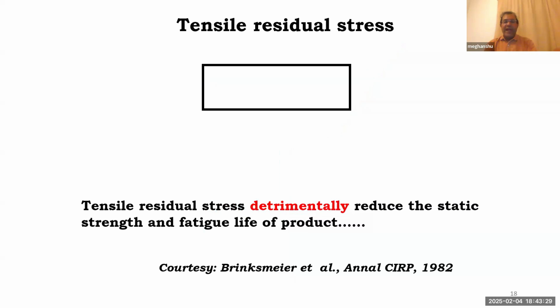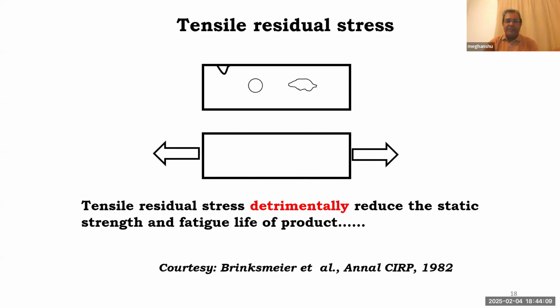So, if we consider this block as a component and this component is having cracks at surface level, the component is also having void or free space. It is also having some porosity. So we know all manufactured components or any produced product is not 100% accurate because it is having all these imperfections or impurities. So if the component has all these impurities and it also has tensile residual stress, which will elongate the component in this direction, what will happen with these cracks, porosity, or void? All these will get enlarged like this. You can see enlargement of crack, enlargement of void, enlargement of porosity. So when these get enlarged, they will detrimentally reduce the static strength and fatigue life of the component.